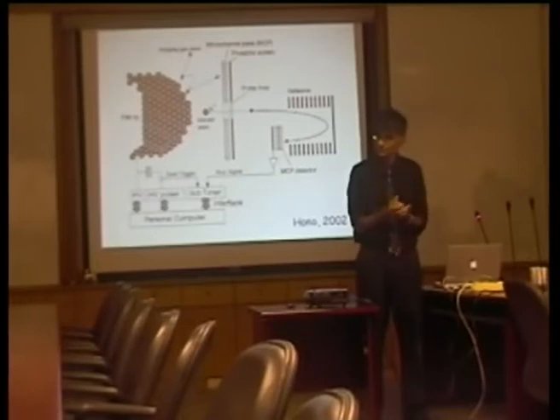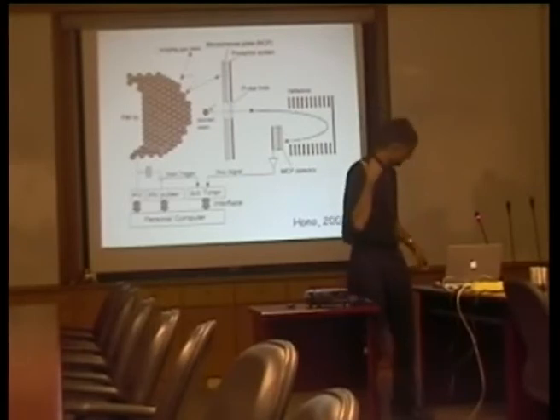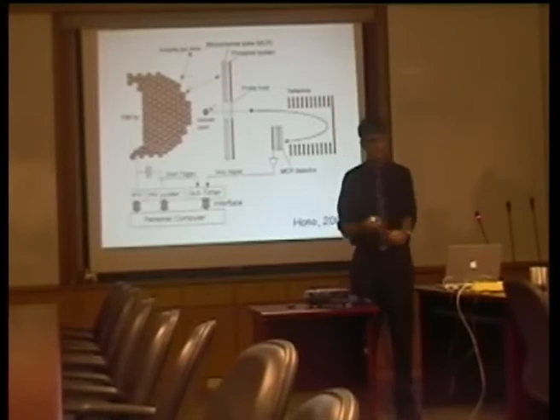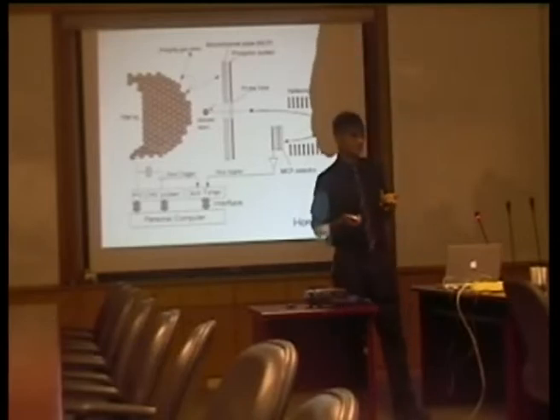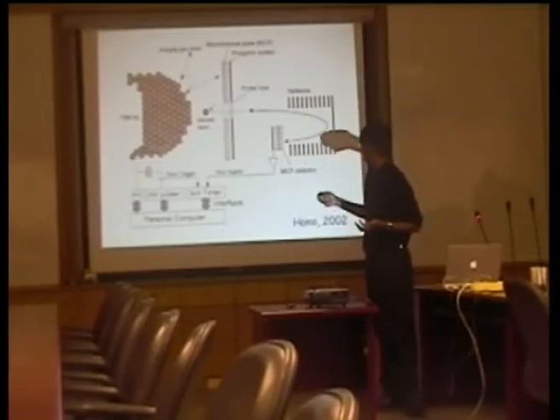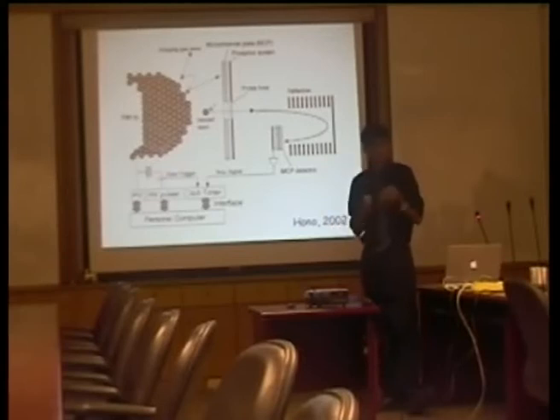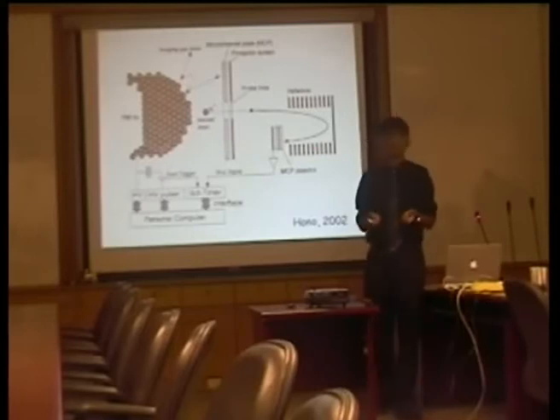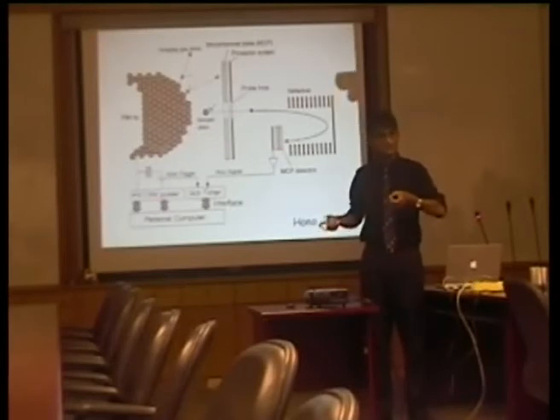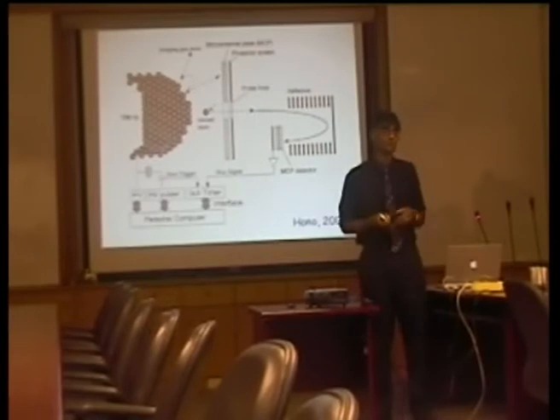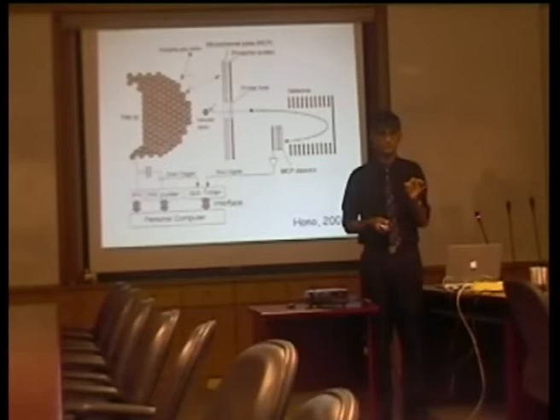And of course, you can use high-resolution transmission electron microscopy, or you can use field ion microscopy. Field ion microscopy is illustrated here. You make a very, very sharp needle. And on an atomic scale, that needle won't be sharp. It will look something like this. It will be blunt. But it's still very sharp from our point of view. You then apply a large electrical field to it, and that allows the atoms to follow the trajectories of the electrical field, and you form an image over here with a magnification of more than 10 million. So you can see individual atoms.